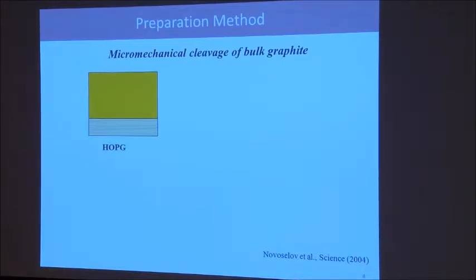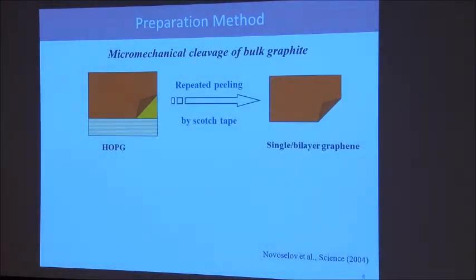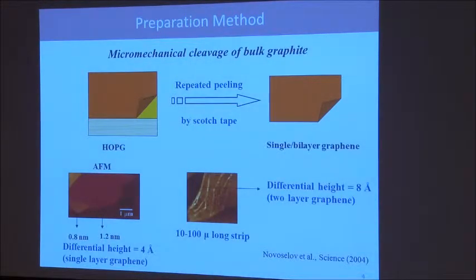Now, how does one make it? What these people did was take a graphite crystal, put a Scotch tape, and peel off the top layer to get one graphene layer. This is nothing new; people tried this 50, 60 years ago, but had no way to characterize what they got. Today we know what you get when you peel off a layer with Scotch tape. You can get a single or bilayer graphene, measure the heights or thickness of these, and know whether you have one or two layers by micromechanical cleavage.